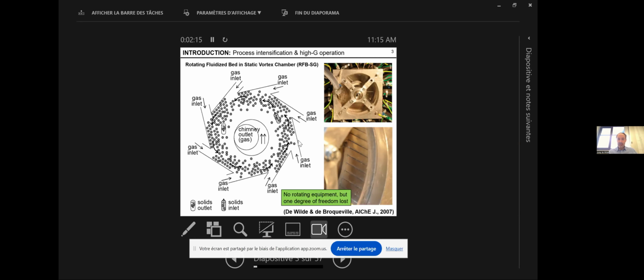And that is, for example, drying ultrafine powders, cohesive powders. They agglomerate, they stick together when fluidized against Earth's gravitational field, so you cannot properly fluidize them. In a high G field, the van der Waals forces that are responsible for that agglomeration become relatively unimportant, yeah, because the other forces become more important. And so then you can do things that you cannot do normally.